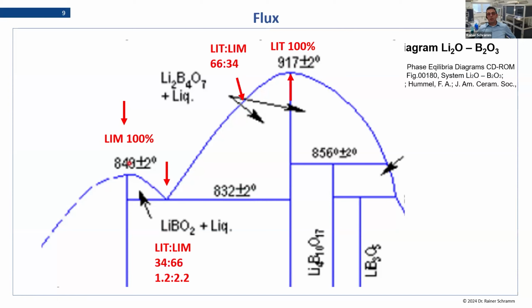So you see how the melting point depends on the flux we are using. And it's not only the melting point, it's also the behavior of forming a stable glass. While lithium tetraborate is a glass former, so it gives immediately a stable glass, lithium metaborate is not. It just crystallizes, directly forming a crystalline solid. If we cool down lithium tetraborate quickly enough, we still have a liquid frozen into glass. That's how we can say it. Okay, so this is very important. You have to look at the melting point here, and you have to look at how easily you get the glass, and this is better on the lithium tetraborate side.